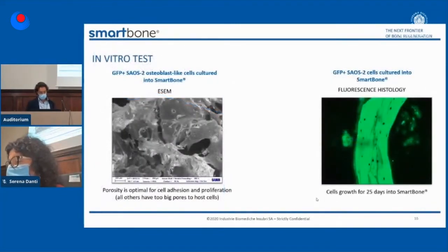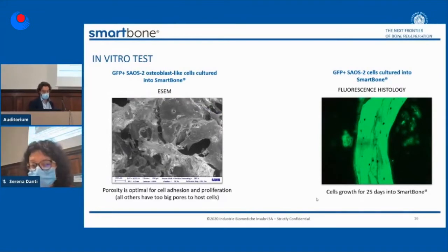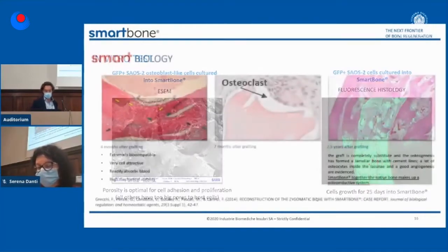Here you can see some in vitro analysis. You can see that the cells are very well spread onto the surface of the bone. From histological information, in green you can see the bone, the cells, but you cannot see the polymer. So you can see that the cells can connect to the surface of the polymer. And then after the degradation, they start to create a layer onto the surface of the bone.